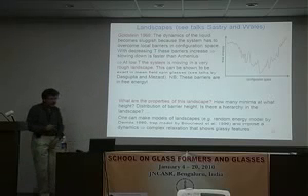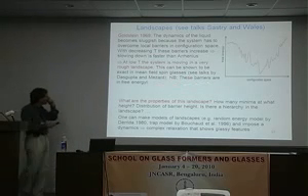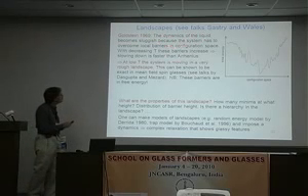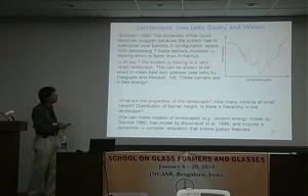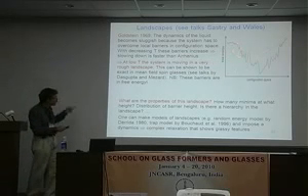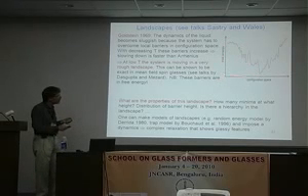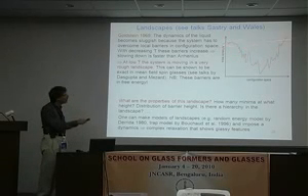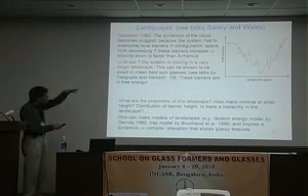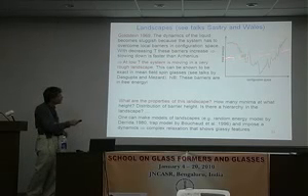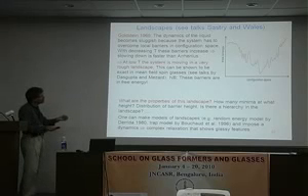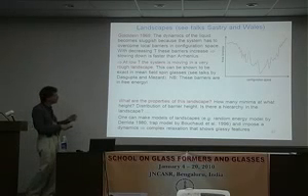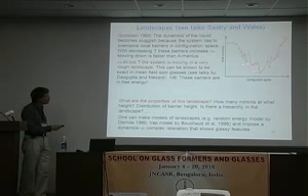Okay, landscapes. Here I'm not going to talk much about this, because there will be other talks by other people. The idea here was invoked by Goldstein 40 years ago: for a glass-forming system, the free energy landscape as a function of configuration space is very rugged. If you are at high temperature, you are populating states that are up in the landscape, what Austin was talking about yesterday. If you decrease temperature, the system will populate states that are down here, and these barriers between adjacent states start to increase with decreasing temperature, depending on your system. For a fragile system, that's the case. And therefore, at low temperatures, you are moving in this very rugged landscape.